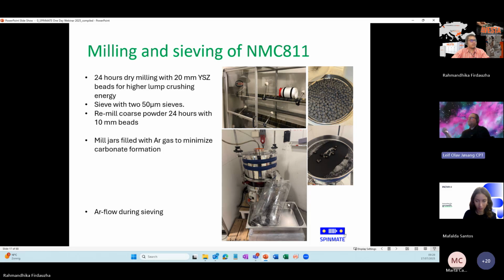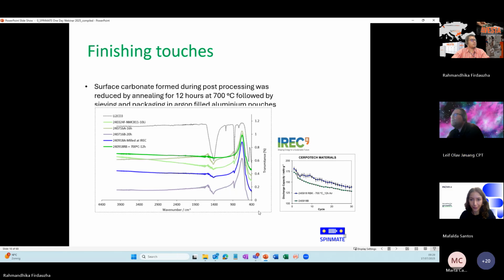All the powder that passed the sieve, whether after 24 hours of milling or 48, IREC found had a varying but significant amount of carbonate on the surface. It was not enough to show up on our XRD, but they could detect it by methods that are more sensitive to surface conditions.